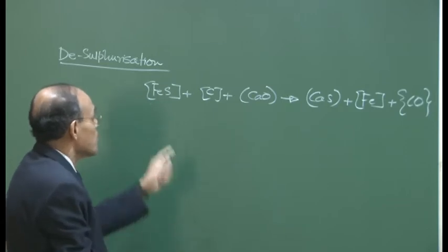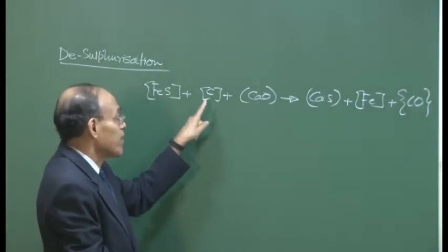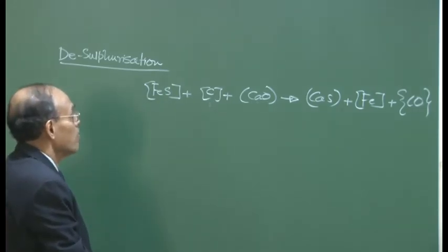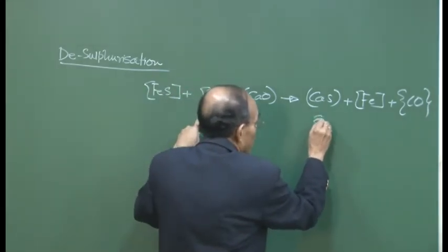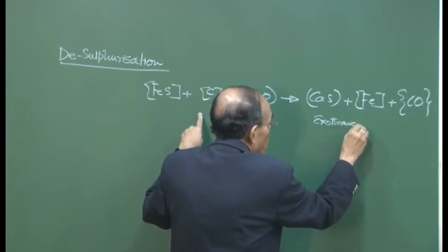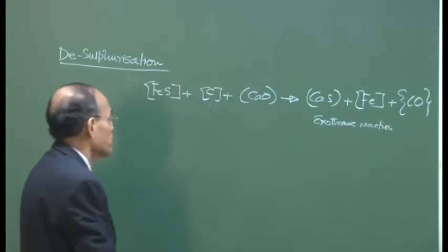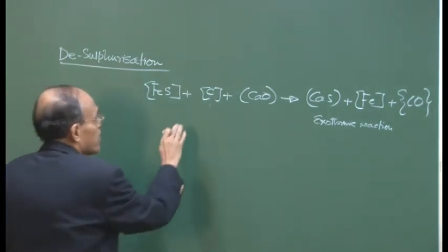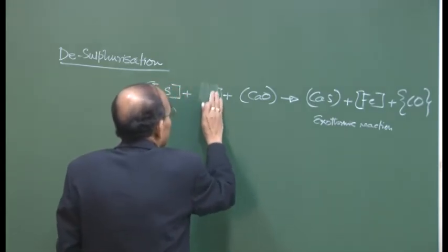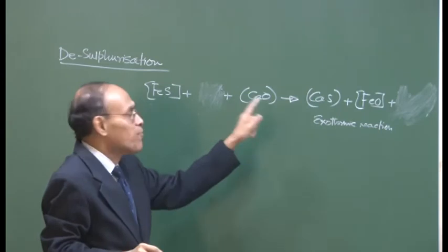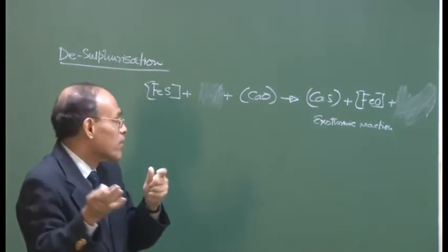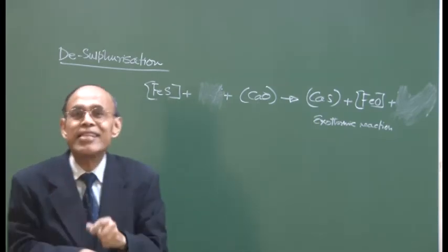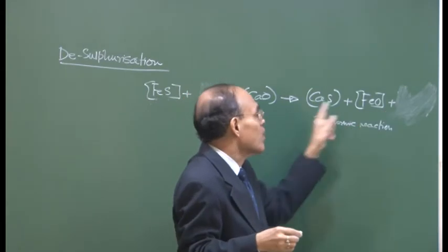And as we have seen, I repeat again, we require a basic environment, we require a reducing environment, the presence of carbon is necessary, and this reaction as such is an exothermic reaction. On the other hand, if you write the equation without carbon, the temperature has very little effect, because the bond strength of sulfur and oxygen with Fe or Ca are almost of the same intensity. So the temperature does not have a very significant effect.